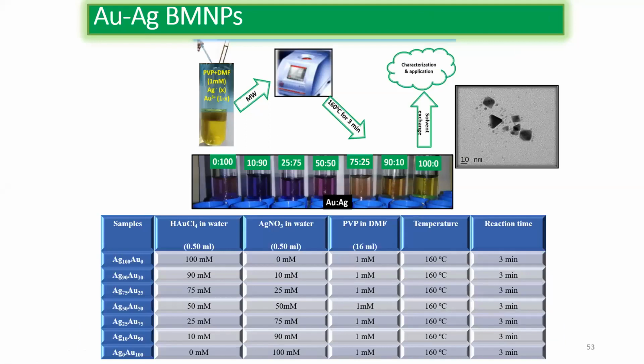I have made silver and I have made gold, but gold is very costly. So why can't I make a silver and gold alloy? An alloy will not oxidize, it will be more stable, and it will be cheaper also. And I can easily tune the color just by changing the silver and gold ratio. So I made alloy by using different silver and gold nanoparticles.